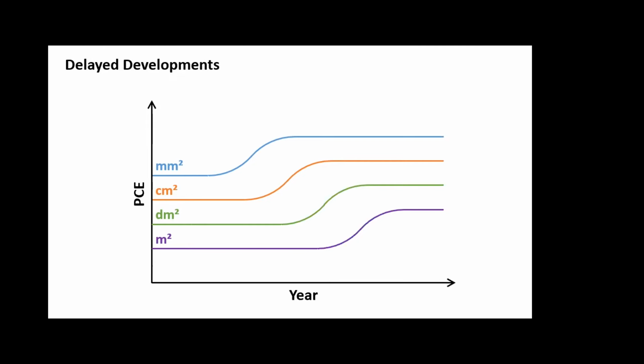So if, for example, we are now at a point where we see this steep rise in efficiency during the last 3 years, I think we had 5 absolute percentage points in record efficiency on a square millimeter level. This cannot be seen on the big module level yet, because those processes just need time. The materials are not available. They need to be synthesized on a larger scale, and so on. So as long as there's a steep increase in the development on the square millimeter side, there will be a larger discrepancy between the different device sizes. But no worries, in the end, it will get narrower again.